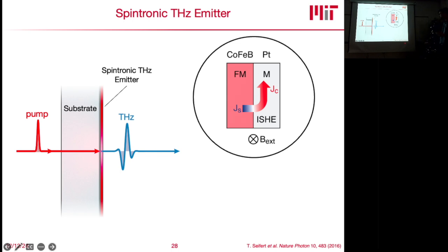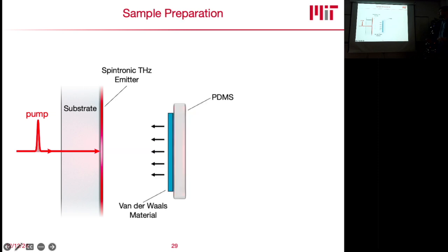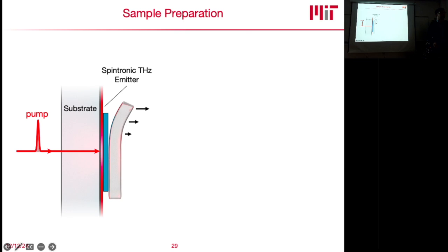And of course, I cannot take any credit for this because these things have been around for a while. But they are now turning out to be incredibly useful for what we want to do. And so the idea now is to bring your sample, which is here a Van der Waals material on a PDMS stamp, and deposit it on this terahertz source to make use of this pump pulse, which we can focus arbitrarily small. So we can create a terahertz source that's tiny, that's right next to our sample.